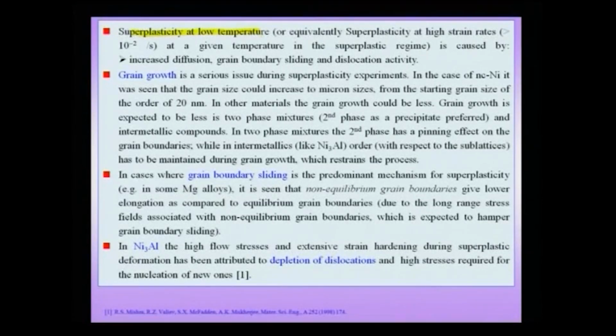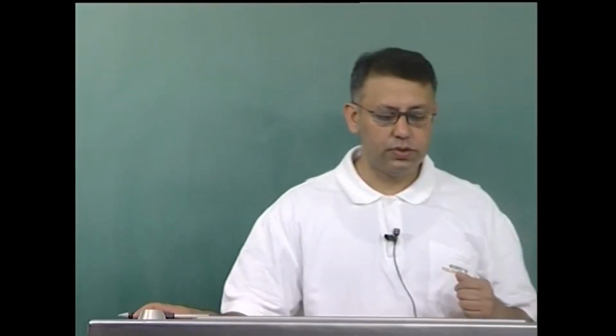So, we now need to worry about what the mechanisms underlying this superplasticity are, and what issues we need to address if we want to understand the results correctly. Superplasticity at low temperature, or equivalently, superplasticity at high strain rates at a given temperature in the superplastic regime, is caused by increased diffusion, grain boundary sliding and dislocation activity. We have already seen that when you go down to nanocrystalline sizes, it is usually the grain boundary sliding mechanism which becomes prominent, and this grain boundary sliding has to be accompanied by some diffusion and dislocation activity. So, this seems to be the overall picture regarding how superplasticity is obtained in nanocrystalline materials, at either high strain rates or at lower temperatures than what you expect for the microcrystalline counterparts.